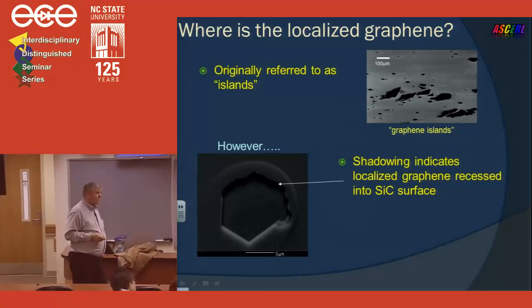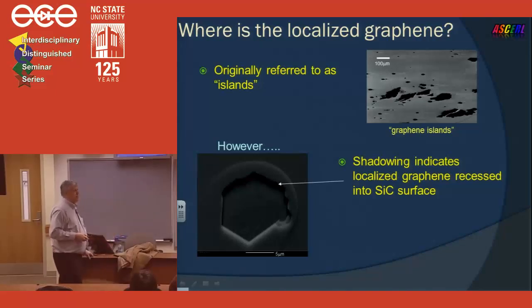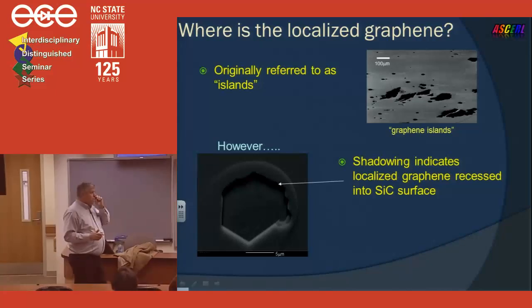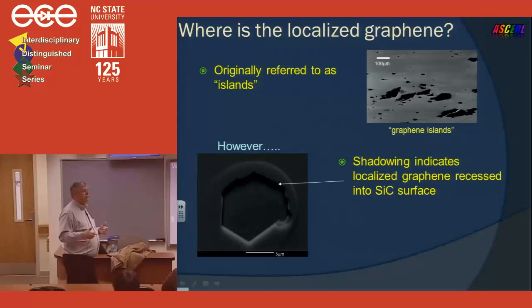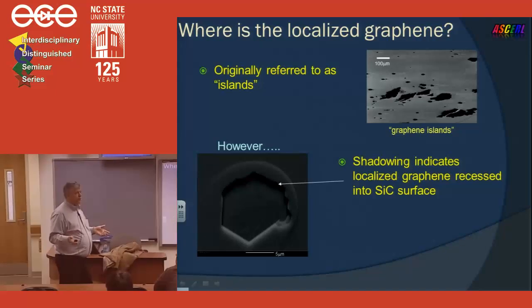I cannot visualize a dislocation in one monolayer. Well, it's really threading up from the substrate, and it's just penetrating the surface. Yeah, so it's coming from the substrate. But if you have graphene by itself, it should be no dislocation. Right. What you're going to find out is that the threading screw dislocation is a conduit for silicon sublimation, and that allows the carbon atoms to diffuse out.